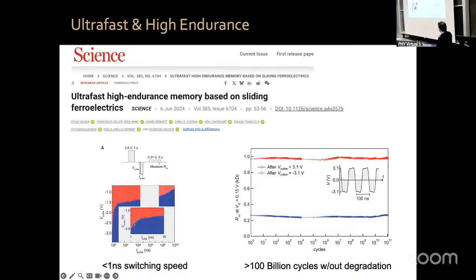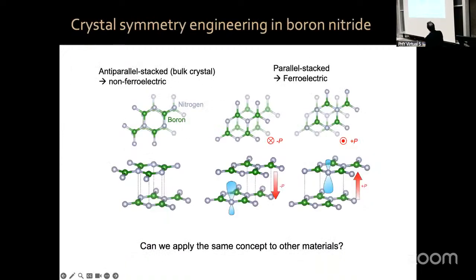This thing can switch over 100 billion cycles without degradation. Maybe we just got bored of switching this thing after 100 billion times. That's higher than pretty much any other ferroelectric in the world, and this works all at room temperature. So the community is getting very interested in this type of sliding ferroelectricity, a new type of ferroelectric that we didn't see before. The same thing you can do—